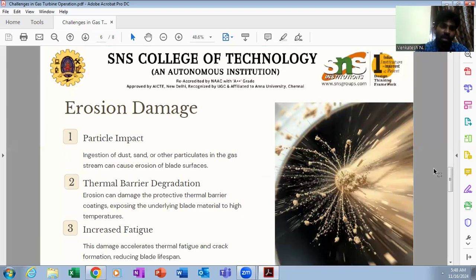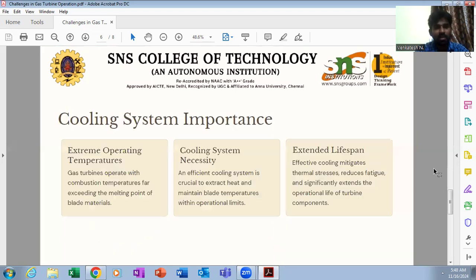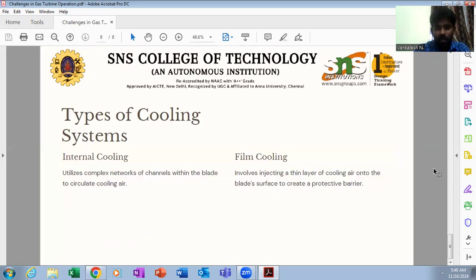And erosion damage: particle impact from ingestion of dust, sand, or other particulates in the gas stream can cause erosion of blade surfaces. Thermal barrier degradation: erosion can damage the protective thermal barrier coatings, exposing the underlying blade material to high temperatures. Increased fatigue: the damage accelerates thermal fatigue and crack formation, reducing lifespan. And also the cooling system: extreme operating temperatures, cooling system necessity, extended lifespan. The final one is types of cooling, in two categories: internal cooling and film cooling.